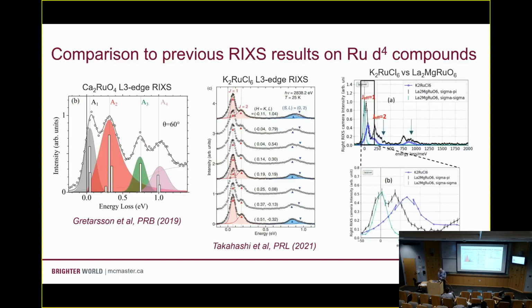and we'll throw our lanthanum magnesium ruthenium oxide on here as well. And we can even overplot it with the potassium ruthenium chloride. And the key parameter that we might be interested in from this excitonic magnetism point of view is the difference between J equals 0 and J effective 1. So how big is that spin orbit exciton gap? When you compare the two of them here, you'll see that in the potassium ruthenium chloride, it's about a 75 meV gap. In LMRO, it drops to about 35 meV.